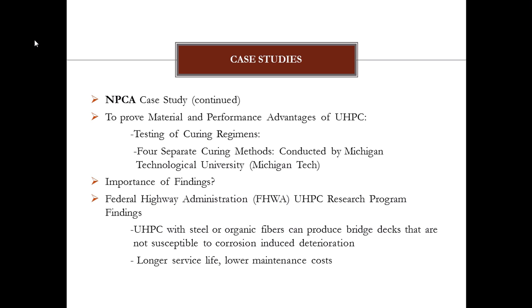The results of these tests were thermally treated specimens attained an average compressive stress greater than 29,000 psi, independent of onset of curing. Air-cured specimens at 28 days had a compressive stress of 24,000 psi. All specimens showed negligible chloride ion penetration. All specimens were freeze-thaw resistant, and the compressive strength, Poisson's ratio, and modulus of elasticity did not vary after UHPC